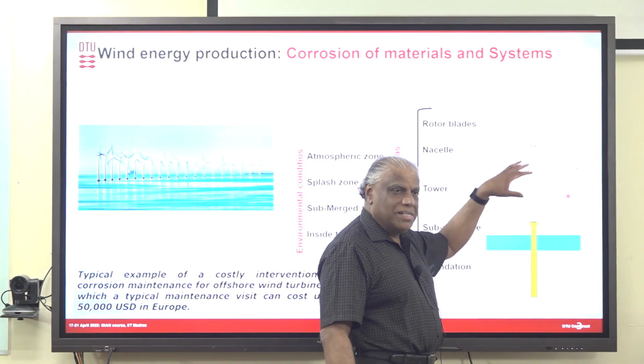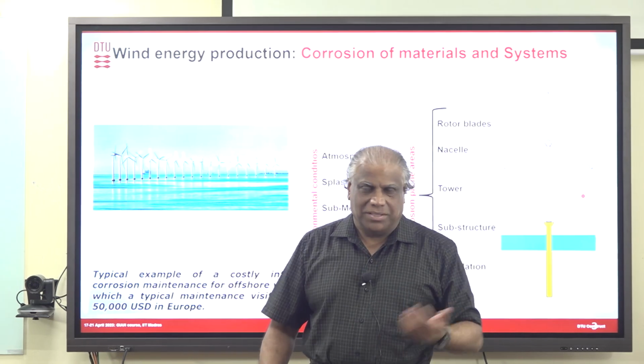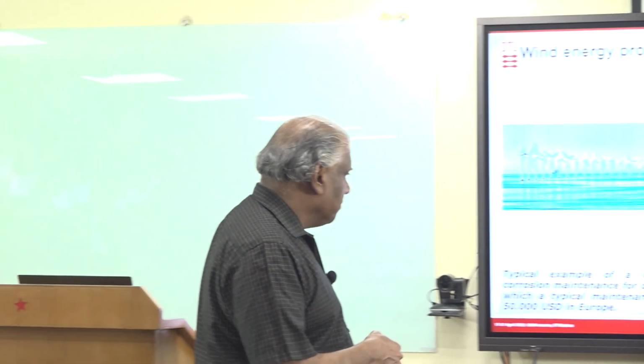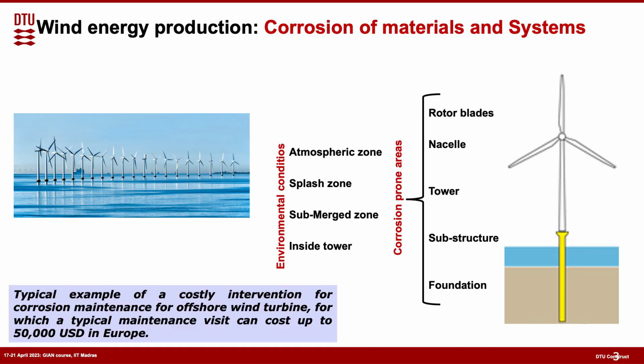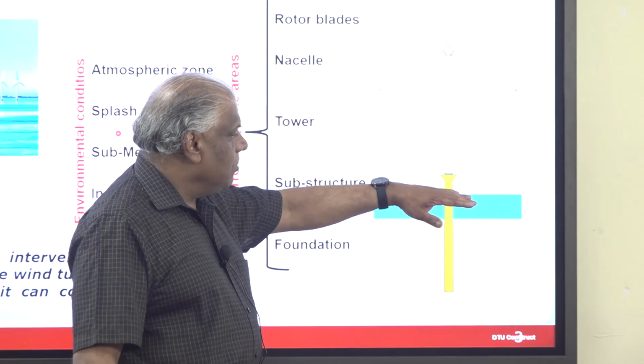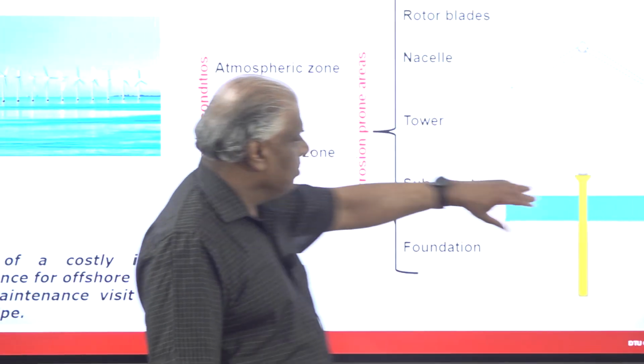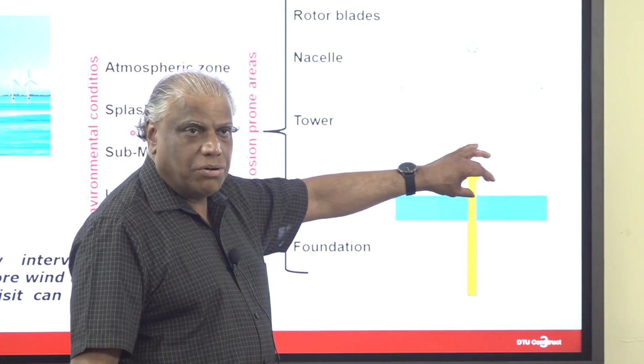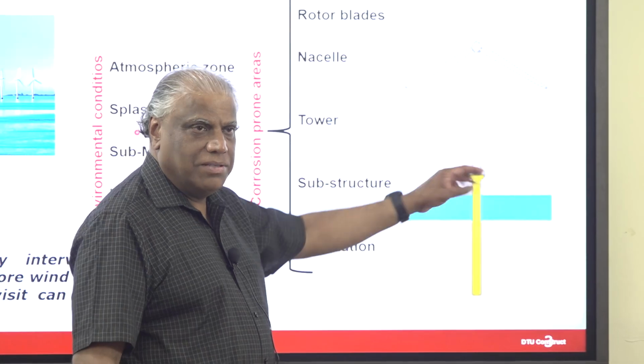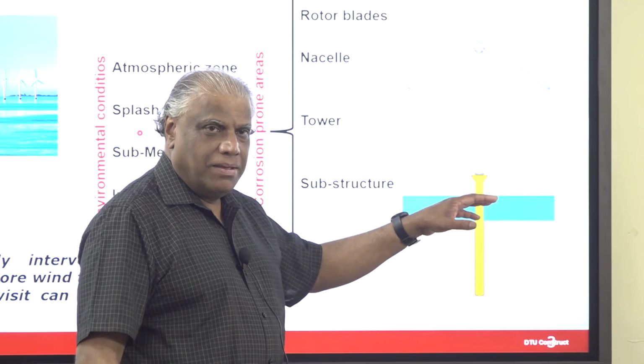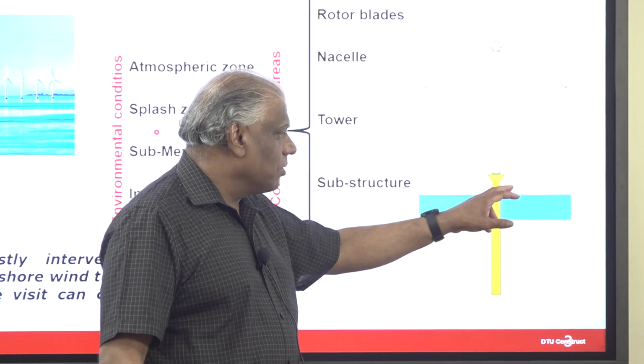So the corrosion inside the tower is also important. It's not simple, because there are so many things sitting there. Inside the tower, for example, there is the submerged zone. If you look here, you have the part which is below the sea, and you have this part that is a splash zone. So you have different corrosion here, because the seawater is splashing, and when the seawater is splashing you get much more corrosion here. Why?